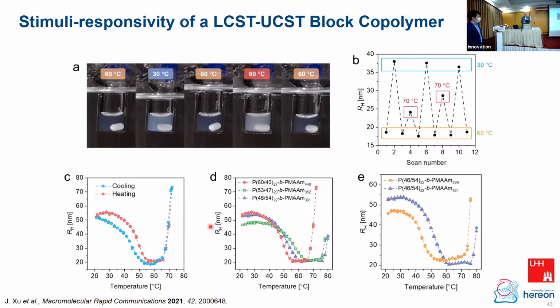Well, I should be careful with this system. We still need, I think, some organic solvent. But I have shown you the system of polystyrene with a PAPU, and that was completely without organic solvent, just by photo-RAFT.